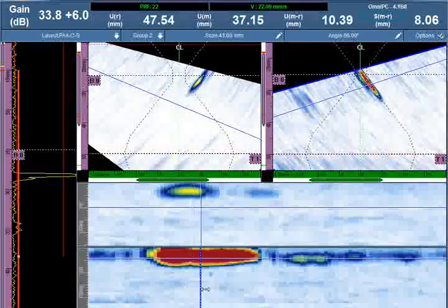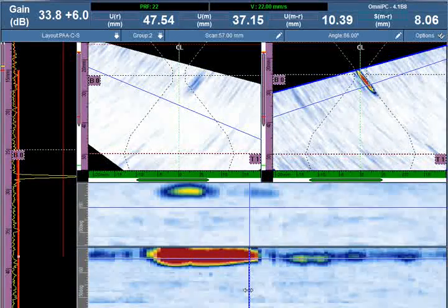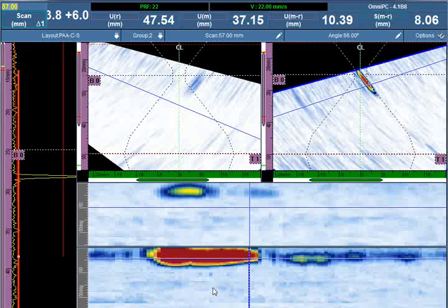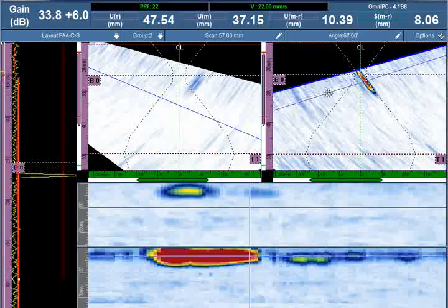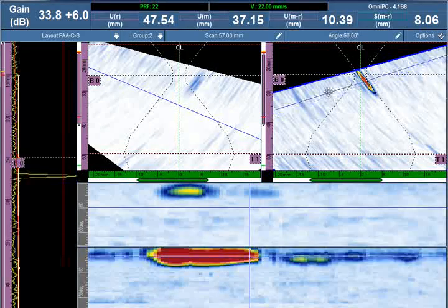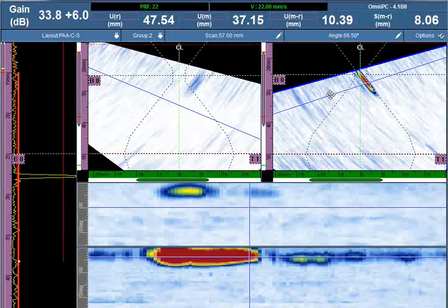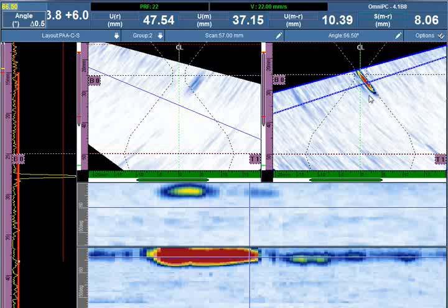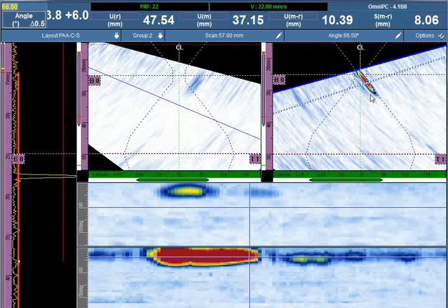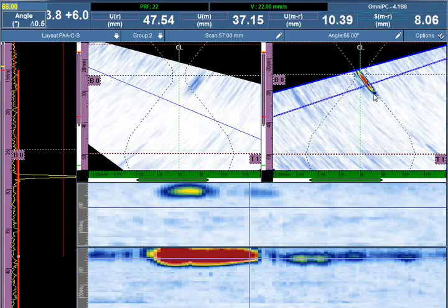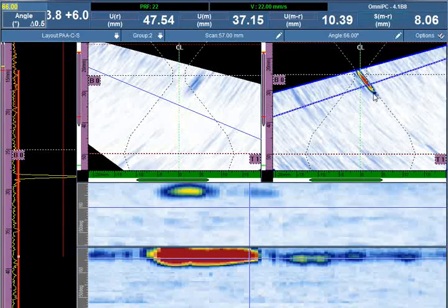Length sizing for the lack of fusion indication is best performed on the C-scan. The lack of fusion is near perpendicular to the orientation of the beam, and it is a large linear indication that is larger than the beam, indicating an amplitude drop sizing technique using the color palette and A-scan amplitude will return best results.